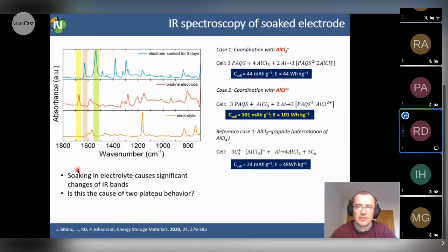Finally, I would like to show you our calculations and give you a message out of that. As Pepe said at the end of his presentation, the quantity of electrolyte is important. And even though we are using these organic molecules, we were able to detect also chlorides coordinating the quinone groups. And the question was whether we have a monovalent or a divalent coordination. I can say we have something in between. So it's not monovalent and it's not divalent. It's a larger ratio of divalent coordination, but of course it's not trivalent.